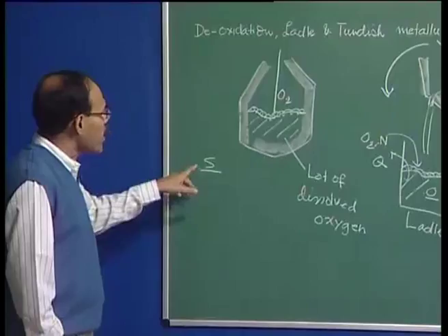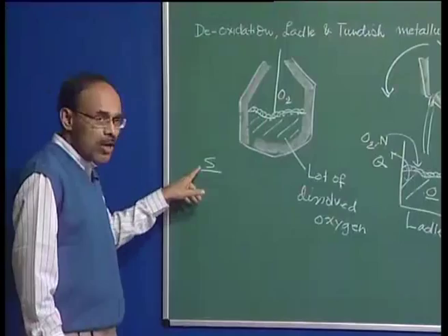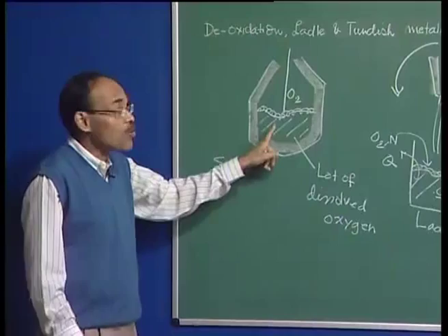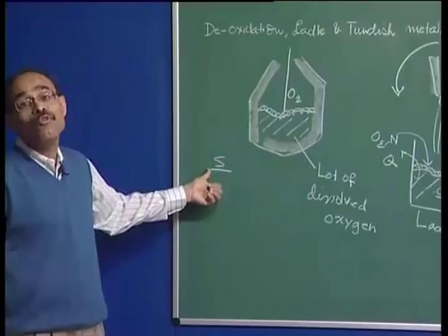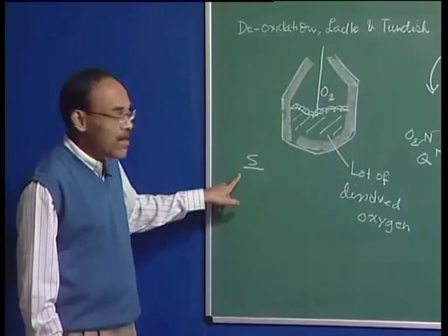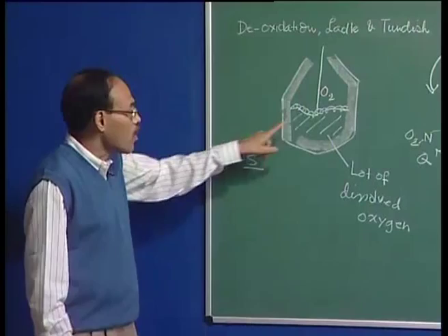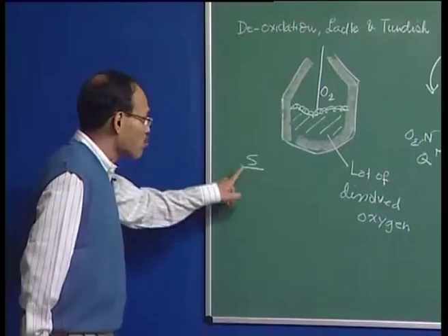well. So, we can have a lot of sulfur in the basic oxygen furnace, and we know why sulfur is going to be there, because the conditions in the basic steel making furnace, or BOF, are not conducive for the removal of sulfur, because removal of sulfur requires a basic and reducing environment, and that is why in primary steel making, which is an oxidizing process, sulfur removal is not facilitated. We have to carry out sulfur removal under a reducing condition, as we will see later on.